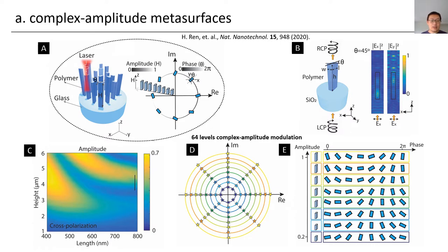And then we simulated this cross polarization response in the amplitude part. You can see that the vertical axis is the height of the 3D nanopillar metal atom, and the horizontal axis is the length of this metal atom, where we can select this black dashed line here to control the different amplitude, just like the different height, where we can also rotate the nanopillar to control this geometric phase. That ends up with the 64 levels complex amplitude modulation, which is very useful for many optical experiments that I will explain later.